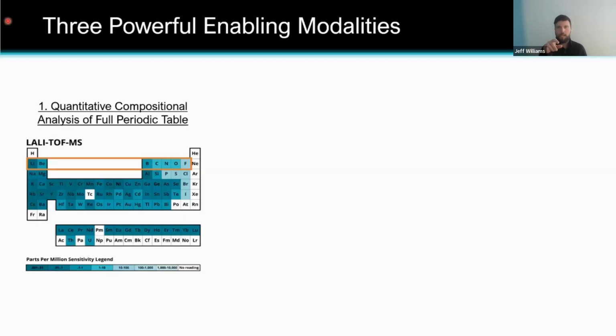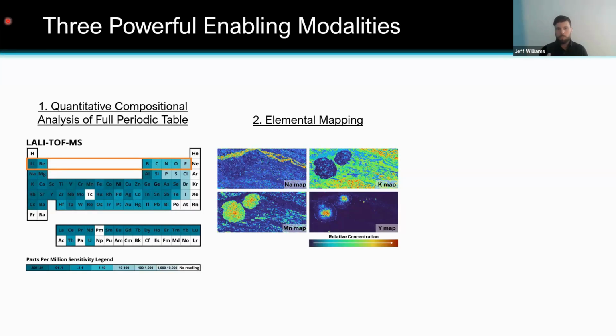So every pixel, right? And now we're going to move that sample in space. When we do that, we can create a chemical image. So that's our second modality, is we do quantitative compositional analysis down to low parts per billion level. And at every pixel, then we can see where that chemistry is happening. And what you're looking at here is a map of a thin section that we've done that took about 20 hours to do by another technique. We did this map in 20 minutes. And at every pixel, we have the entire periodic table, even down to the low levels of yttrium inside of this one mineral grain that you're looking at there.